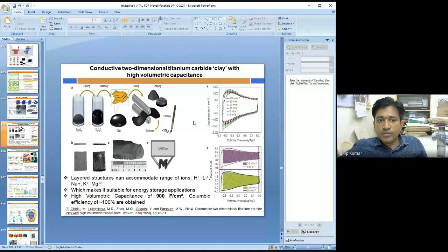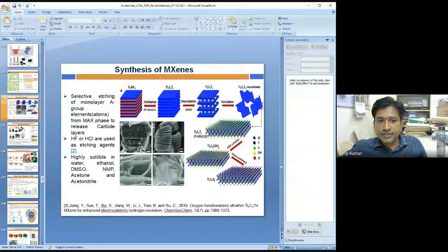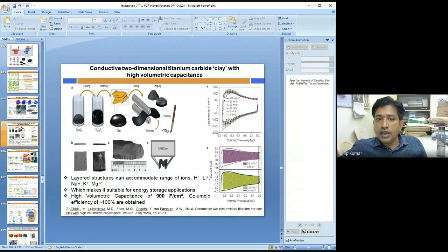High volumetric capacitance. You look at the value, 900 farads per centimeter cube, and maybe almost 100% coulombic efficiency if you go by this titanium carbide. Here titanium is M, and X is carbide. So this is what MXenes are, where A is etched out. This is the synthesis of MXenes leading to high volumetric capacitance and coulombic efficiencies.